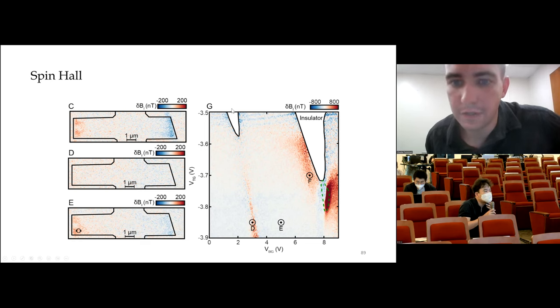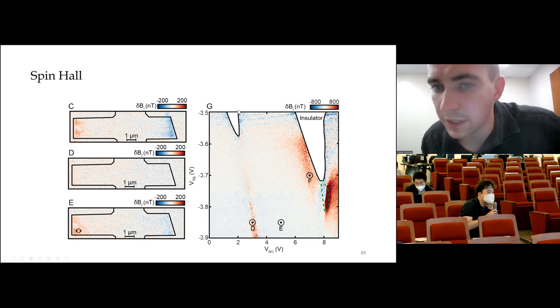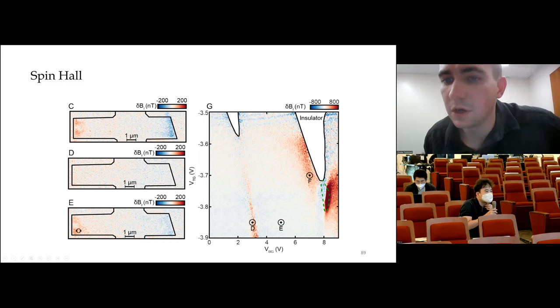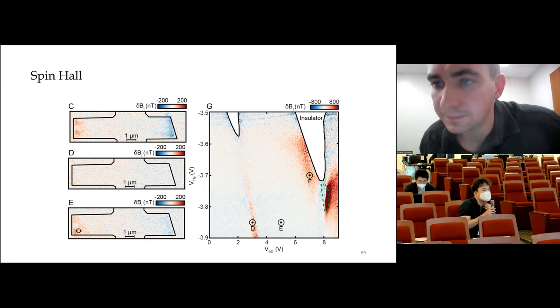This is a phase diagram with the same axes as I showed in the transport data earlier, and this region is where we see flipping. This is the quantum anomalous Hall regime, but over a wide variety of regions close to full filling of the Hubbard band, so close to one hole per unit cell, we see a large increase in the spin Hall signal. We understand this to be associated with populating electrons into states with large Berry curvature and anomalous velocity.